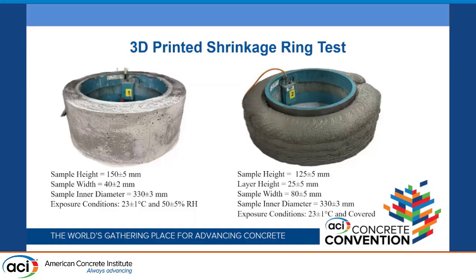However, we wanted to generate these cracks naturally, so we did a modification of the shrinkage ring test, where we decreased our height and increased our width to make it castable, and made slight modifications to exposure conditions since we didn't want to disturb the sample in its fresh state. Instead of moving it into an environmental chamber at 23C and 50% relative humidity, it was kept in lab conditions and covered with plastic, slightly changing the drying behavior but still allowing the test to occur.